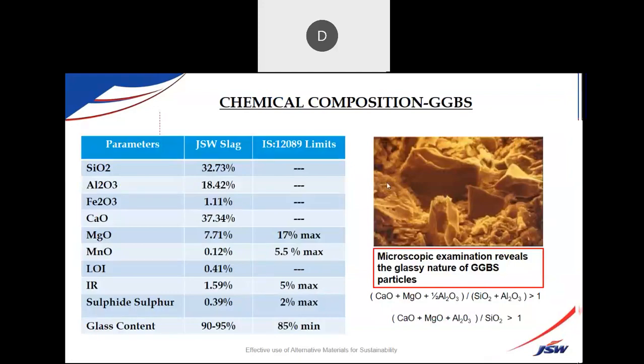Apart from the chemical composition, we have various parameters. As per the earlier code, IS 12089 talks about the raw slag, blast furnace slag. We have tested the JSW slag along with the standard specification given as per IS 12089. In all the parameters, the JSW slag being manufactured surpasses the requirements. Even the glass content is 90 to 95%, whereas the requirement is 85%.